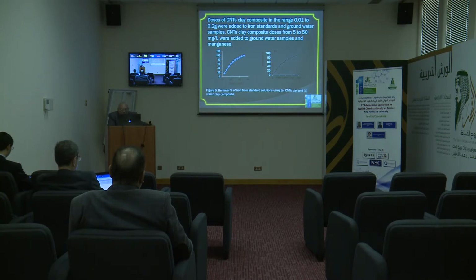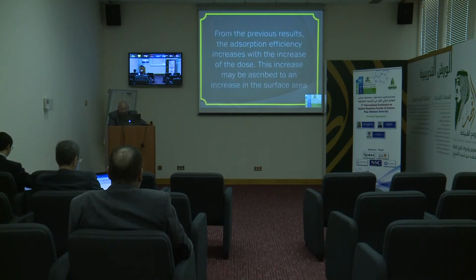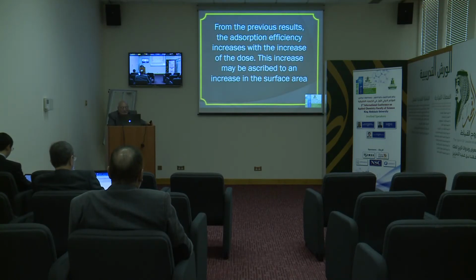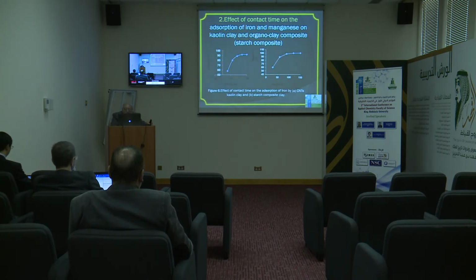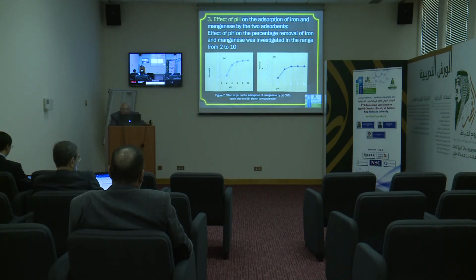The doses of carbon nanotubes clay as representative, the removal percentage of iron from standard solution: A using carbon nanotubes clay, and B starch. It is clear from the paper that the adsorption efficiency increases with the increase of the dose. This increase may be ascribed to an increase in the surface area. Effect of contact time, as you see in the figures, also increases with time.